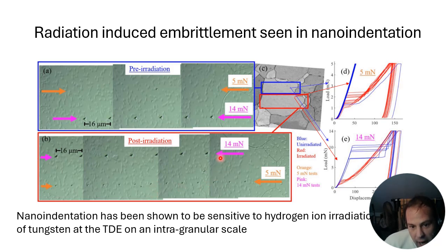When you load it up to a higher load, 14 millinewtons in purple, in the pre-irradiated specimen, we see that at 14 millinewton loading, the yield load is something like 10 millinewtons. The load at which it transitions from elastic to plastic is about 10 millinewtons. And after irradiation, the load at which it transitions from elastic to plastic is something like 2 millinewtons.